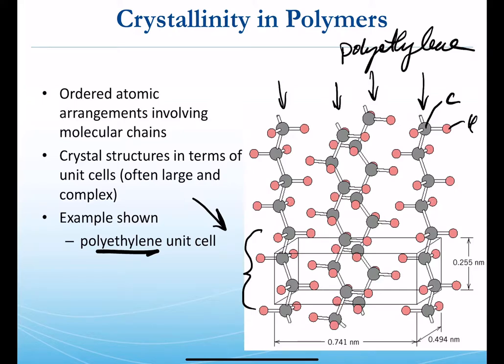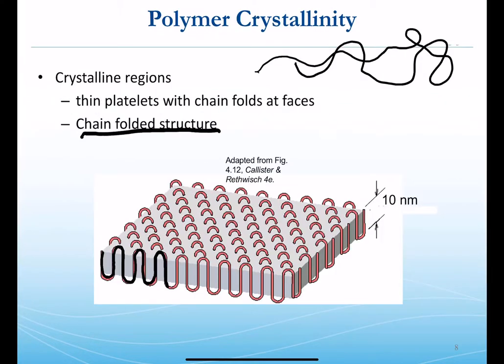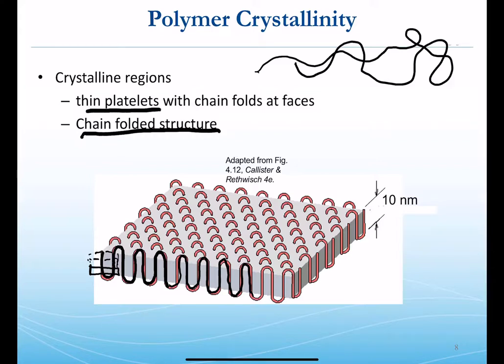This could be not four different chains, but the same one chain that has looped on itself, packed back into the lattice, and then packed to another site and back in again. So the unit cell on the previous slide might only represent a very small piece of this. Several unit cells would stack up to the point where the folding — which isn't representative of the pattern of atoms in the unit cell — would be regarded as more of an amorphous loop or hook that brings the chain back into the structure. What we're looking at is a thin platelet with chain-folds at the faces.